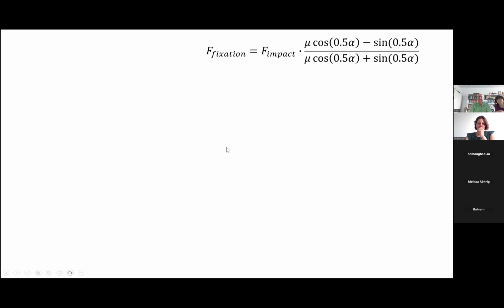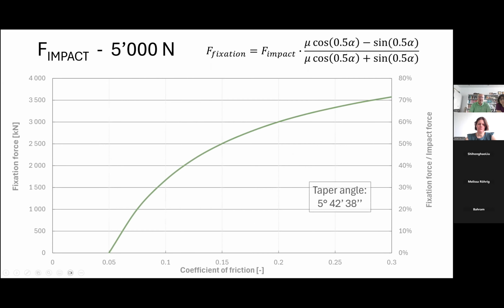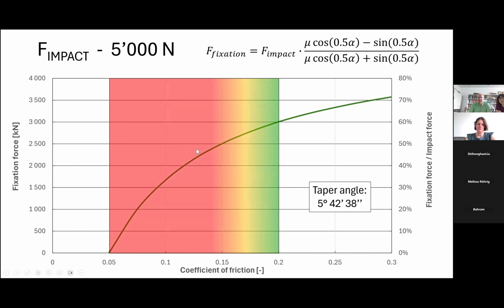And now, if you take this equation, you take an impaction force of 5,000 newtons, and you make a graph where you see here the fixation forces. And here you see the percentage between the impaction force and the fixation force for an angle that we use in orthopedics. You have this type of behavior. I told you if it is dry on dry, you have maybe 0.2. But you can see, for example, if you are decreasing for any reason the coefficient of friction, it is becoming lower. And even if you have a coefficient of friction of 0.05, you don't have any connection.